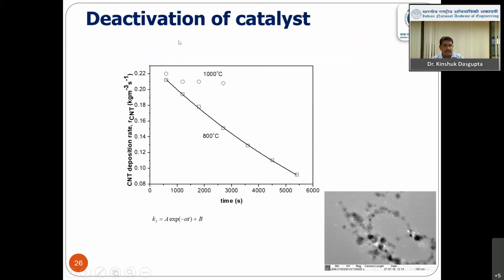We also studied the deactivation of the catalyst. So what happens in deactivation? This is a TEM image where I could show that during deactivation, the catalyst particles get covered with unwanted carbon forms, and then they cannot further catalyze carbon nanotube growth. Like you can see, only one carbon nanotube here just started growing and then it got deactivated. Now what causes deactivation? The supply of carbon molecules should match the growth rate of the carbon nanotube.